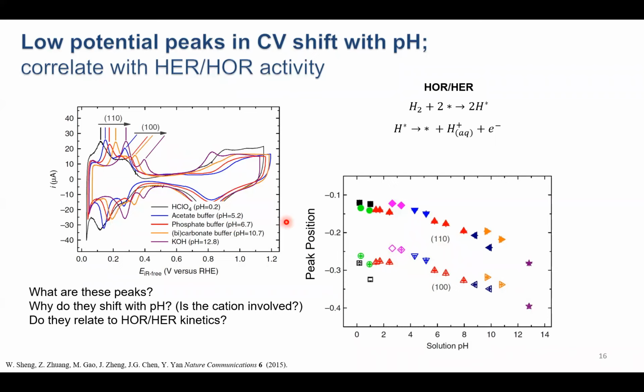And so here I'm showing cyclic voltammograms measured on a polycrystalline platinum electrode. Just very briefly, in a voltammogram, what we're doing is we're controlling the potential of our working electrode, in this case, a hunk of polycrystalline platinum. As we vary the potential, we're driving various reactions which involve electron transfer to become favorable. Different reactions become favorable at different potentials. And when those electron transfer reactions transfer electrons with our surface, we measure that as a change in the current.